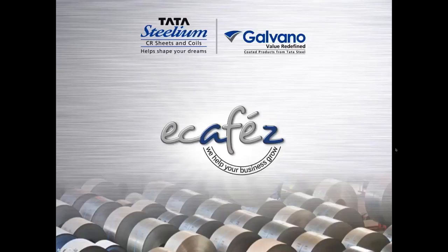Then there is one more question from Mr. Pradeep Kumar Sharma. Can air dry paint be baked in an oven or not? Okay, yes. Basically, not all, but there are some paints which you can put in an oven. It is not called baking. We call it forced drying. Usually at 70 or 80 degrees centigrade, as I have already informed you that the reactions will speed up when we increase the temperature. So this particular hardener to base reaction will definitely increase if you increase the temperature.